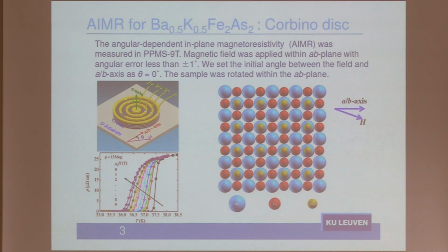It shows how they measured the resistance. This is the Corbino disk design. So you can measure the resistance, then obtain the resistivity. And this is a problem for, I don't know, school probably. The resistance is the resistivity multiplied by the logarithm of the external radius over the internal radius. So we have two circular terminals here, and this way the resistance is extracted.